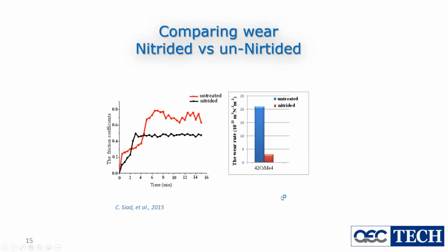How much can we decrease the friction by nitriding? This is research done by Siad et al. in 2015. They show the friction coefficient for nitrided and untreated material. The untreated material is the red line, and the black line is the nitrided material. For the nitrided material, the friction coefficient is about 0.5, and for untreated, it's about 0.7 to 0.8, which is a huge difference.